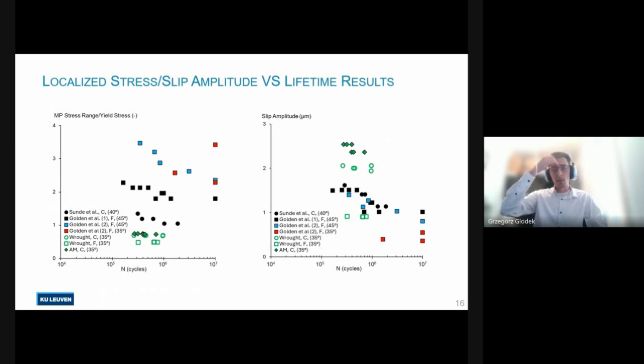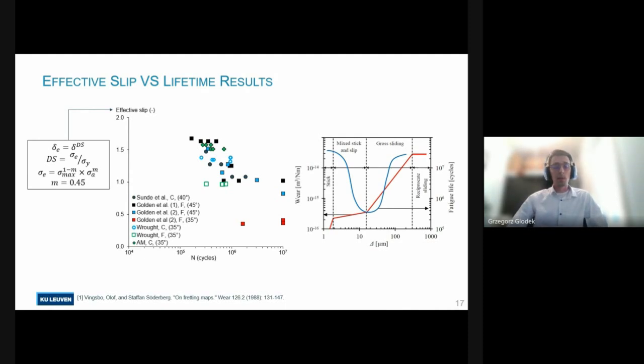But that came with its own set of challenges, as in a lot of the past research, the tests were done at very high stresses far into the plastic region, but that wasn't really addressed in that research back then. So instead, another critical fretting fatigue parameter could be used for comparison, and that is the slip amplitude at the contact edge. So, based on this comparison, the AM material appears to be stronger than the conventional one, but we can take this comparison a step further and include the properties of the material, like the yield stress and the stresses at the contact edge, into a sort of damage severity parameter, which modifies the slip at the edge into the effective slip.